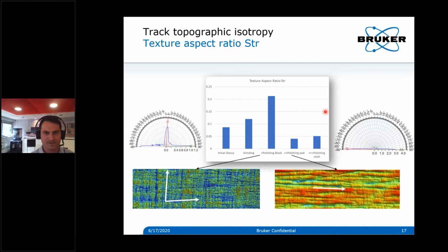The other point is now about understanding texture. So again, whenever we speak about post-processing, what we want is some kind of homogeneous surface. Homogeneous means we want a surface without clear directions. And actually, if we look at the surfaces on the left or this one on the right, you can clearly establish that you have some specific alignments which correspond to how the grinding process was made. So certainly the paths were made horizontally and vertically. And if you look at a polar graph, you clearly see an extension of the roughness power in the horizontal direction and almost at 90 degrees.